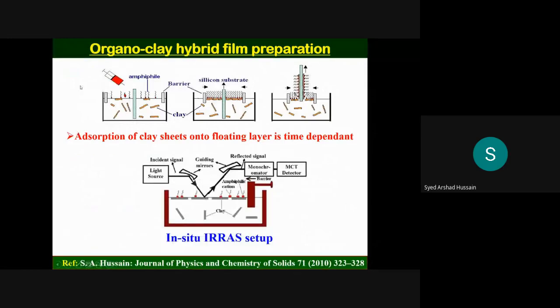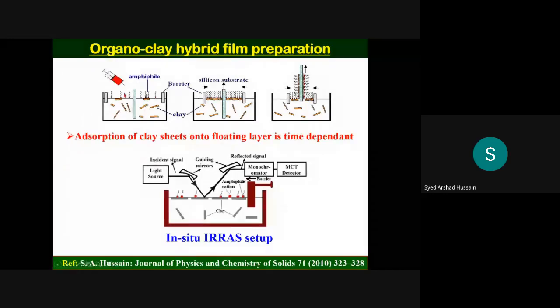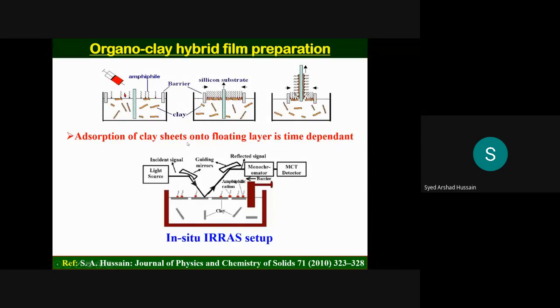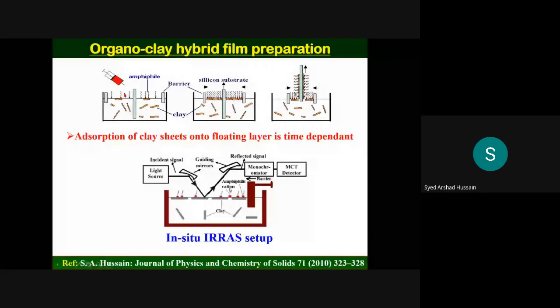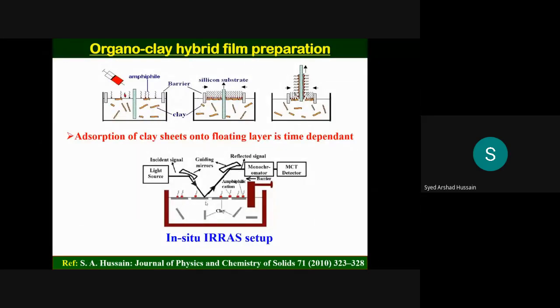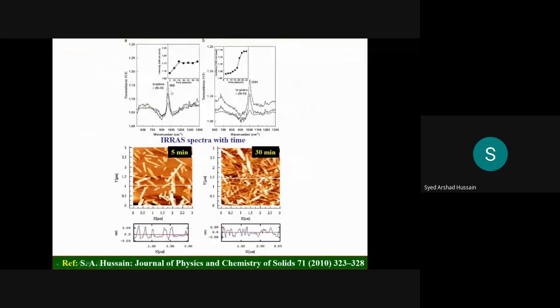And during this film preparation, the floating clay material comes close to the amphiphile. And this is a time-dependent process. One can study this adsorption process by infrared reflection absorption spectroscopy. Here, light is allowed to fall on the surface, and the reflected light is recorded using a detector. And with time, clay materials come onto the surface, that is, the surface thickness increases, so the amount of reflected light increases. Accordingly, the intensity of the corresponding vibration band increases, so one can have an idea. So this is shown here.